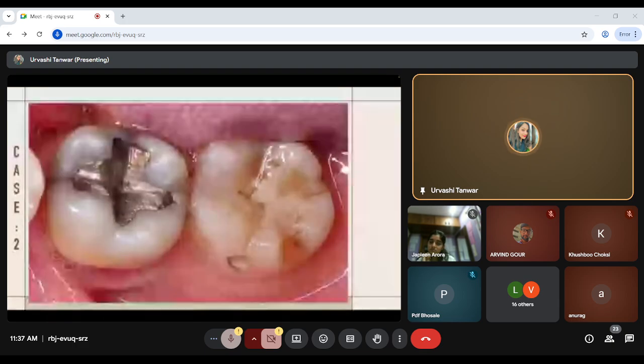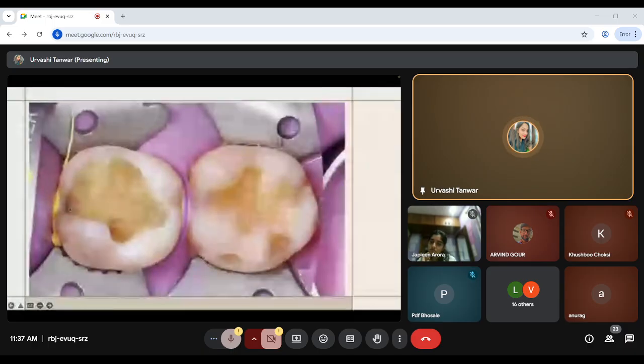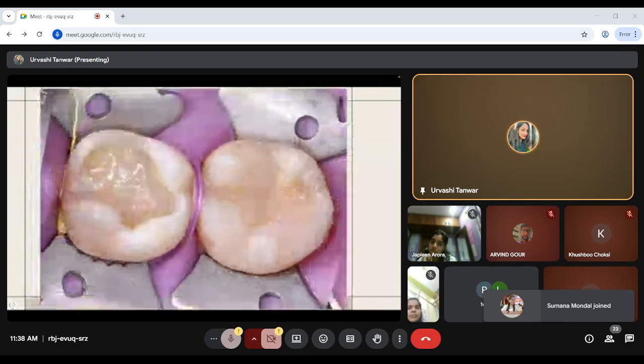You can see the difference. This is an amalgam filling, and I'm doing both the 6 and 7. Look at how when I remove 7, just the tooth, the dentine is so clean. If done properly, it was very clean. But look at what is going on below the amalgam restoration at the mesiolingual cusp. So it needed to be capped. As you can see, the mesiolingual part, the mesial DJ, I've removed the crack completely in the peripheral seal zone. Even in this area, I have removed the crack completely, and the mesiolingual cusp needed to be capped.